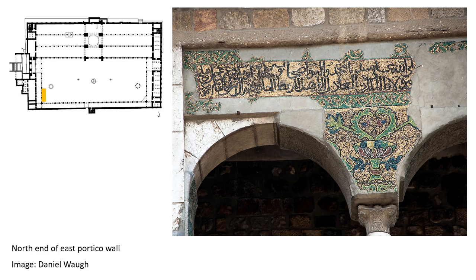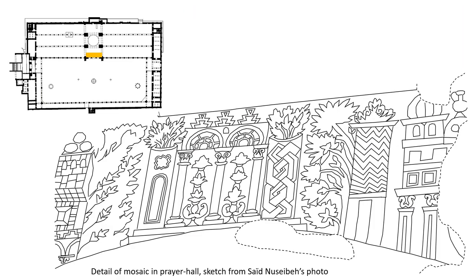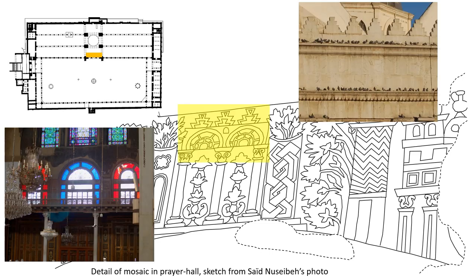Although the letters and the running scroll around them are done pretty neatly, the leaf and vase forms are considerably simpler than any elsewhere in the mosque. The colors of the tesserae on the soffit have also faded, as if the pigment had only been applied to the surface of the tesserae rather than the whole piece of glass being dyed — and I think the tesserae here are probably painted stone, with brighter glass reserved for the more visible facing wall. This all suggests the 1159 additions were done by artisans without the same background of training, or unable to access the same resources, or possibly both.